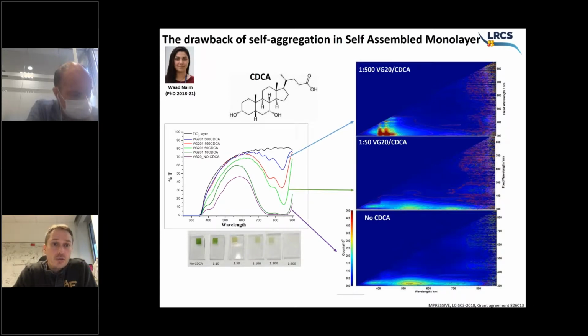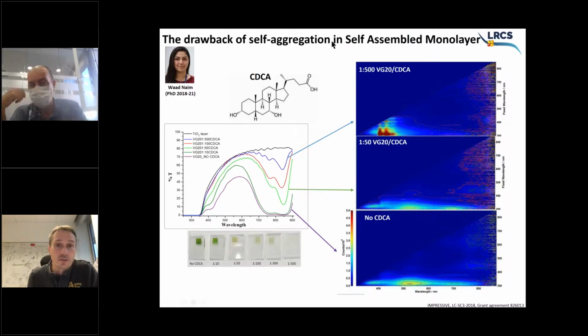Dyes in solution often interact with each other, which forms either head-to-tail aggregation, which is J aggregates, or head-to-head aggregation, which is H aggregation. In solution, we have actually no hints that VG20 is a dye that tends to aggregate. But unfortunately, VG20 tends to aggregate very strongly when it comes into the self-assembled monolayer on the nanocrystals of the anatase. There are different means to avoid this aggregation, and the typical one is using a deaggregating agent, chenodeoxycholic acid, which we call CDCA.